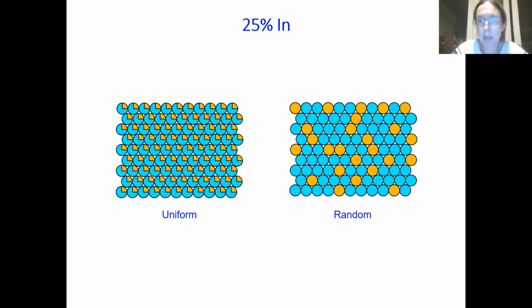Now, the thing you need to know about this mathematical analysis, those quantum wells we're looking at there are 25% indium, and that's 25% indium on the metal sites. So a chemical formula would be indium 0.25, gallium 0.75 N, okay, nitrogen. But something like that, which is 25% indium, it's not that every atom is 25% indium and 75% gallium, obviously not. There are gallium atoms and there are indium atoms discretely, okay? And they are in what we would call a uniform layer.